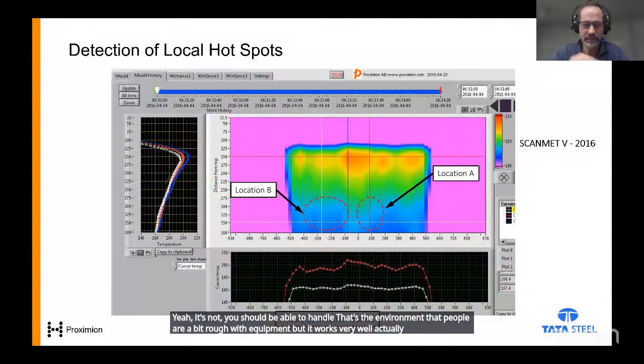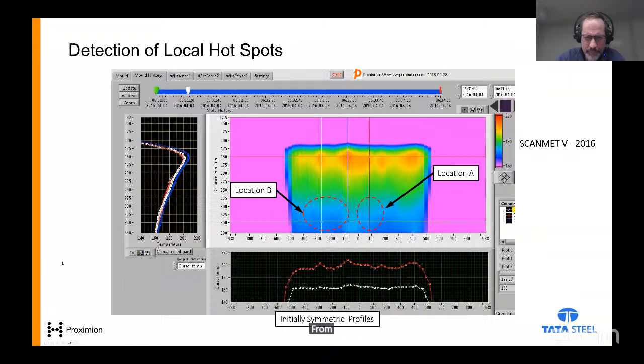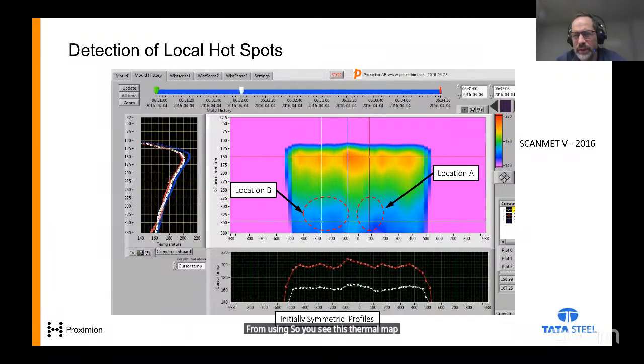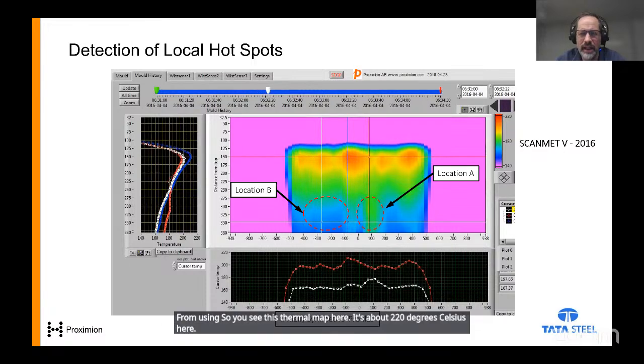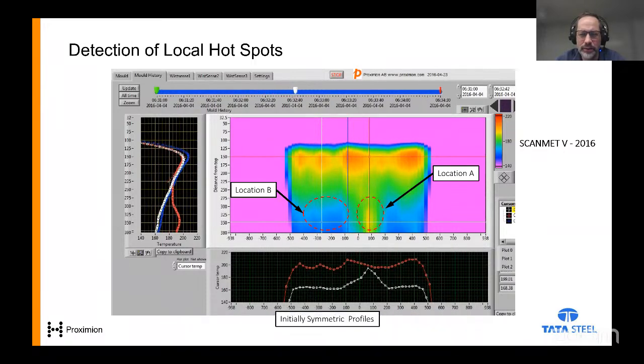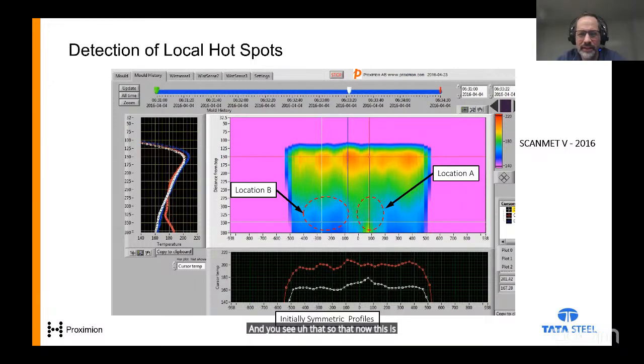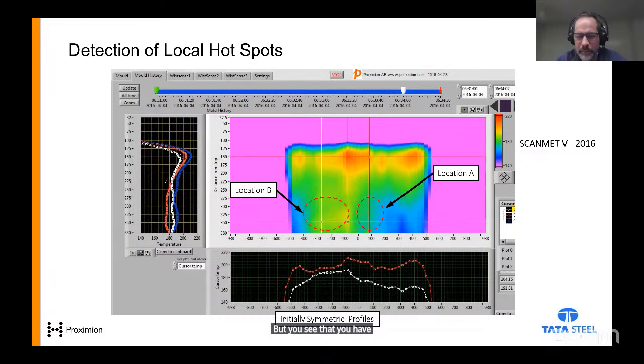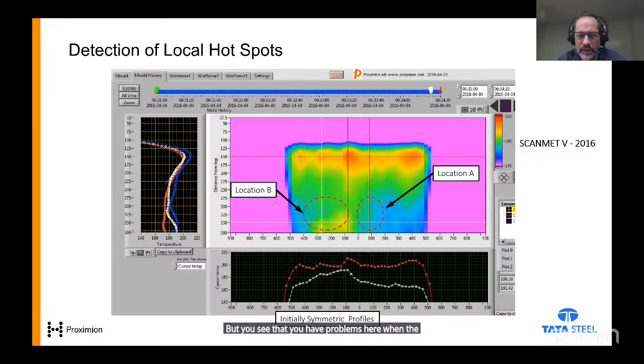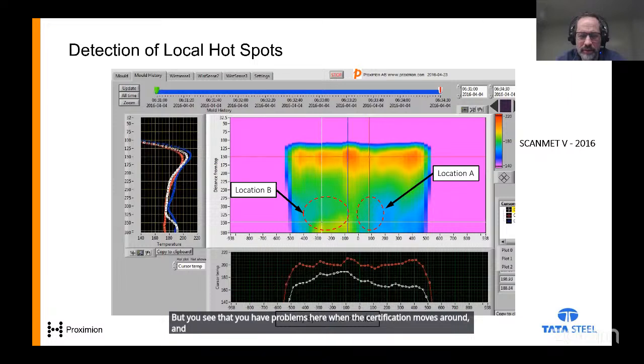This is just an example of what you can see from using it. You see this thermal map here. It's about 220 degrees Celsius here, and this is now accelerated in time. But you see that you have problems here when the solidification moves around, and this could be a case where you could have a breakout, for instance.